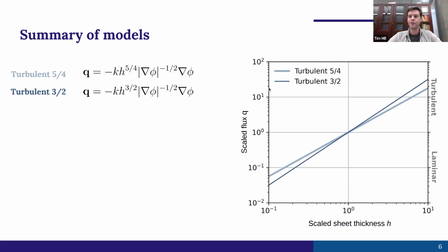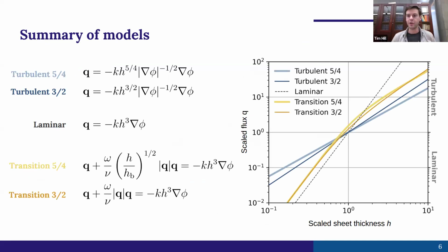To visualize the different parameterizations, I have this log-log plot that's the flux Q versus the sheet thickness H. Of course, turbulent and laminar models just plot as straight lines because it's log-log. The transition models, which I'll be plotting in these shades of yellow, do what we hoped. In the laminar regime, which is the lower left of this plot, they have the same slopes as the laminar model, meaning flow is laminar. As the sheet thickness and flux increase, you get more vigorous flow, the flow transitions to turbulent, and the slopes of the yellow transition lines bend over to match the appropriate turbulent models, depending again on this turbulent flow exponent.